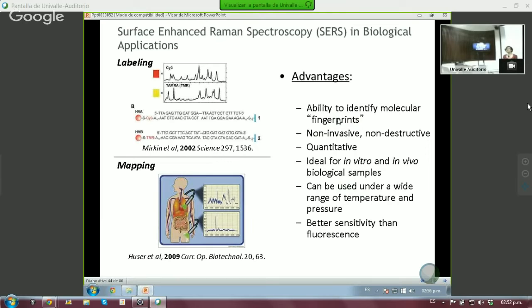Now, you may want to ask me, why do we use two different techniques? Well, it's very simple. What I forgot to tell you is that in the case of all these surface techniques, like the XPS and the TOF-SIMS, we had to take our solution, which is liquid, and turn it into a powder. So there is always this worry that when you go from a liquid solution and make it into a powder, you may have changed how things were wrapped inside. And with the surface-enhanced Raman spectroscopy, we could look at it as it is. But of course, we cannot get so close to the surface as with the TOF-SIMS.